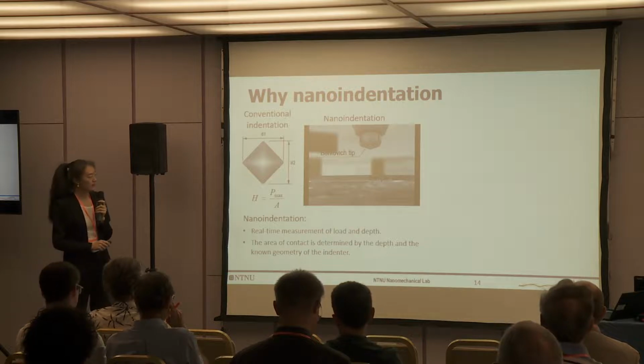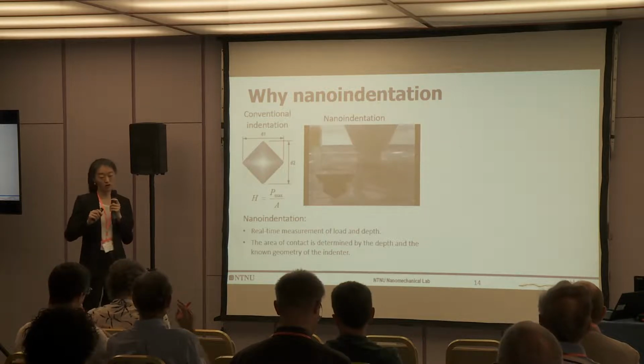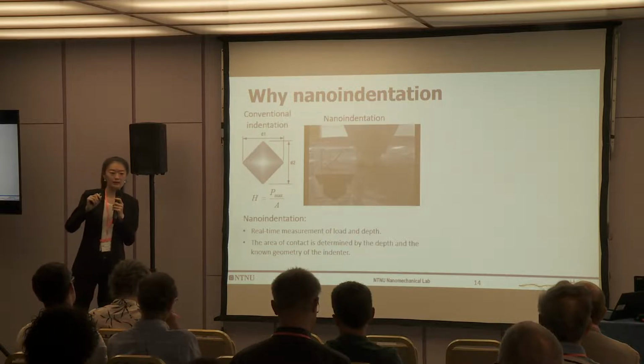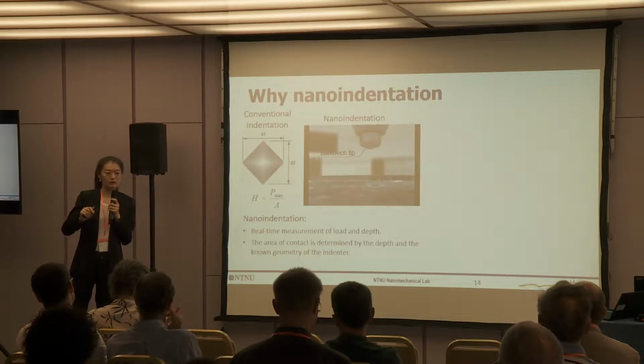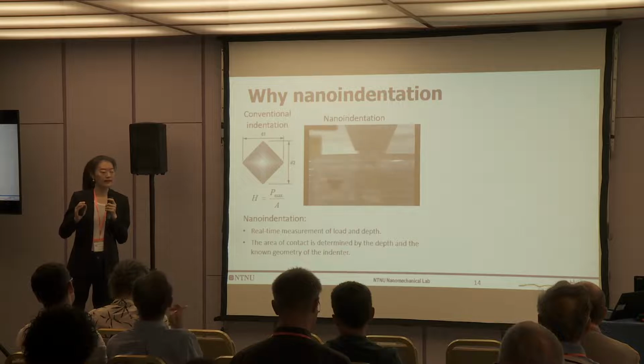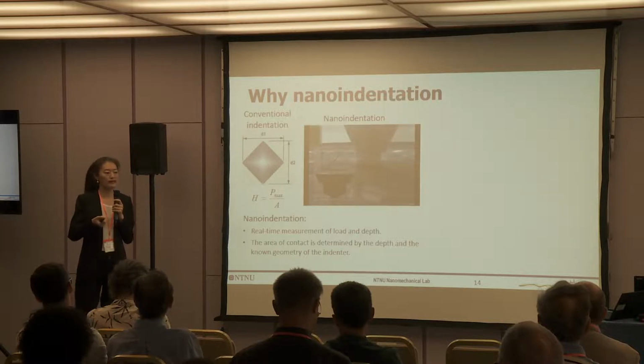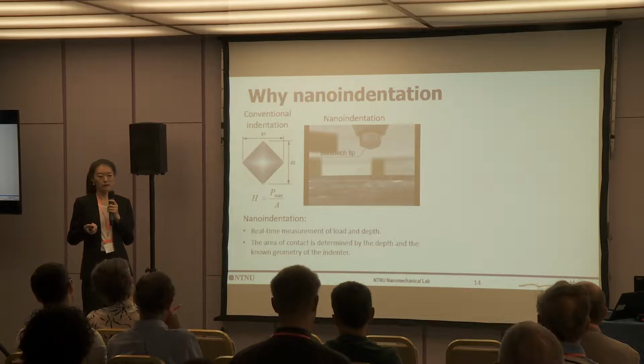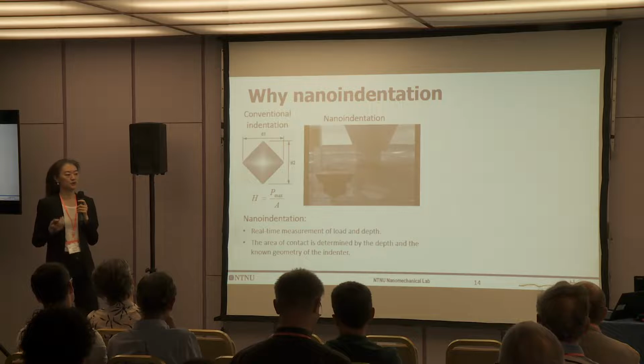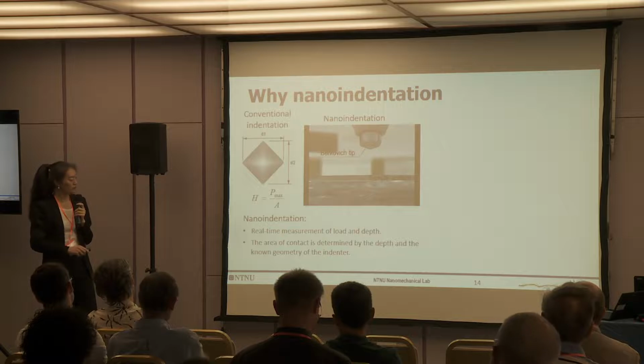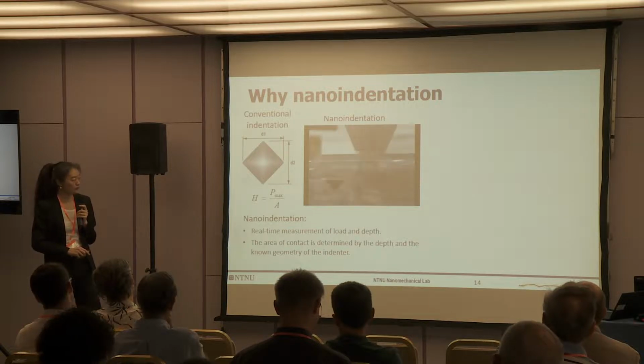And especially, indentation uses a much smaller volume, so it is able to test individual grain and individual phase properties. In other HEAs, if you want to do that, you probably need to use a focused ion beam to cut a small specimen, or even prepare a single crystalline material. But indentation is so straightforward and so convenient to test that. So it's especially suitable for AM-ed materials.